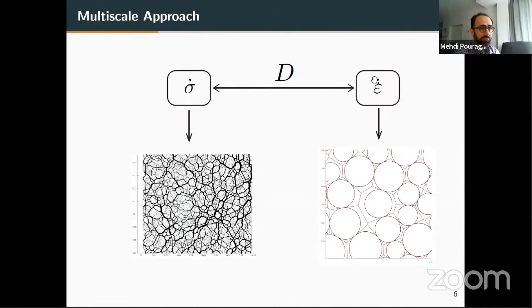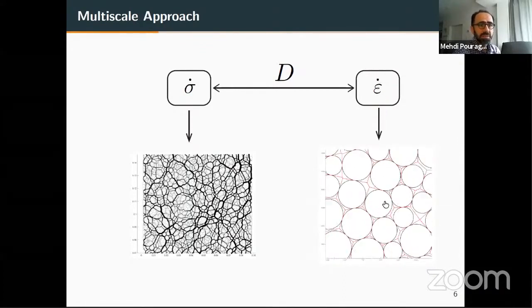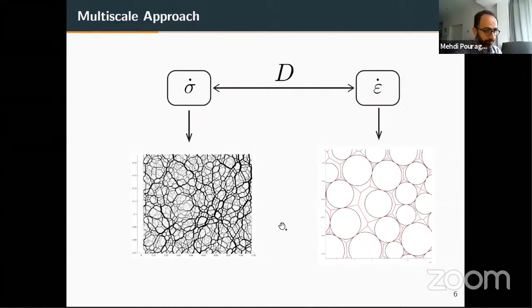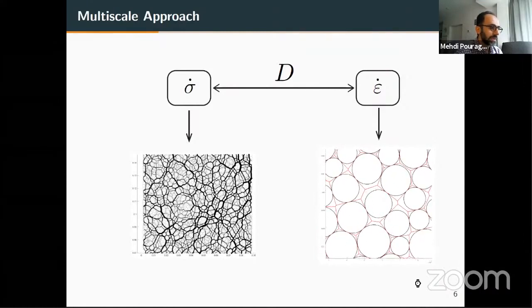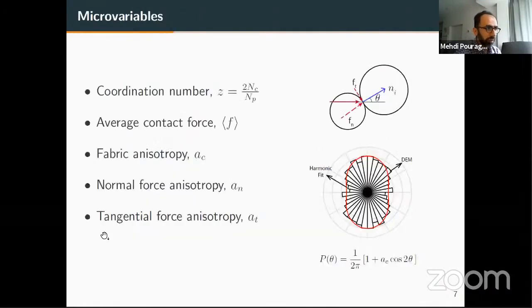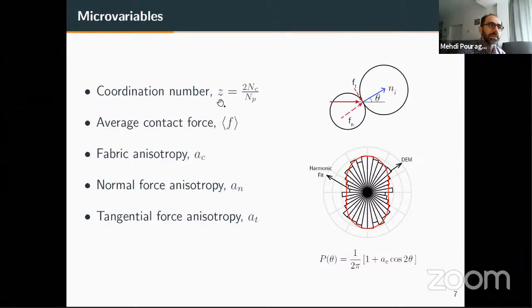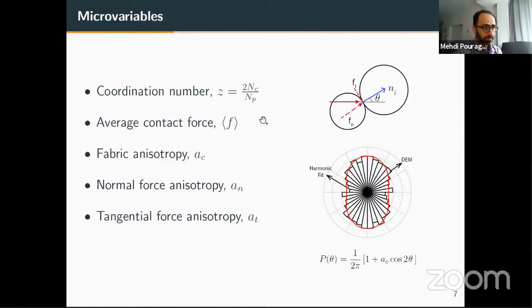And instead of talking about the strains, we are talking about the relative displacement of these discrete entities or particles. So clearly at the micro level, we are dealing with different variables. Some of them that I use in this talk are simple ones: coordination number, which is the average number of contacts per particle, which is closely related to the static redundancy or hyperstaticity of the sample. We have the average contact force, and fabric anisotropy, which is basically the anisotropy of the contact orientation, this vector, and it gives us a measure for anisotropy of the sample. We also have anisotropies for normal and tangential forces, but I'm not using these in this talk.